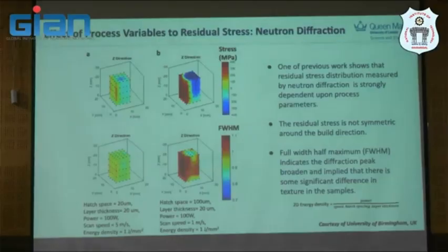Residual stress is also a problem that we found. I think I showed briefly previously, we went to Oak Ridge National Lab as well during my time at University of Birmingham. And this is CM247, I think. You will see the residual stress profile across these actually 30 or 40 voxel point measurements here. You will see the profile is not homogeneous anymore. It's quite asymmetric and heterogeneous in general. This is partly due to the defect content in the sample, and the printing condition contributes to that as well.